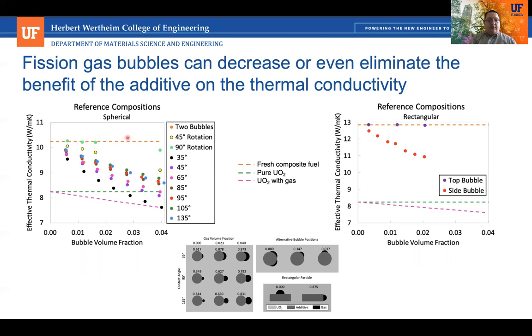But then as we put them in the direction of heat transport, we get an increased effect as we increase the volume fraction, but the slope is directly impacted by the contact angle. So the more wetted they are around the particle, the more it blocks heat transport, to the point where in the extreme cases where we have very small contact angles, so 35 degrees and 45 degrees, and especially let's look at the 35-degree case, as we get even just to 4% fission gas, we've completely eliminated any benefit of our particle. It's as if that fission gas bubble was just sitting in the UO2 without any additive at all.